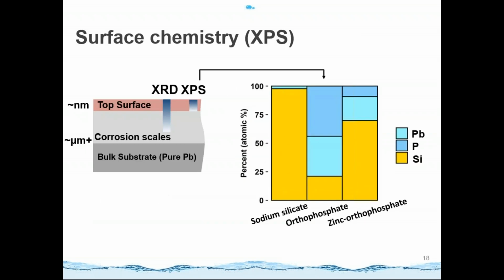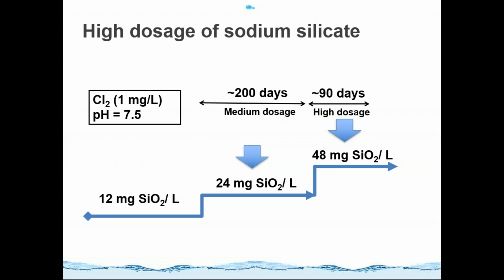But I have to mention that due to the lead concentration data we got, we do not have any evidence to say the silicon-rich coatings can mitigate lead release. So then we tried to investigate the impact of the dosage of silicon on lead release. So we compared the lead concentration at 24 milligram silicon dioxide per liter and 48 milligram silicon dioxide per liter.